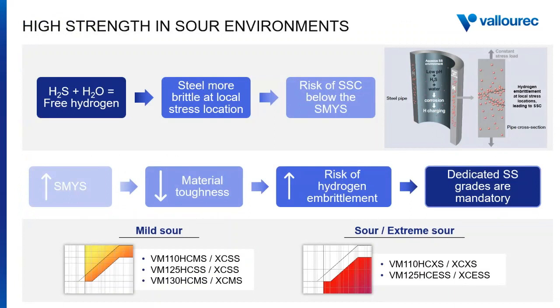This is related to the discussion we had on this slide, because we said that when the material becomes more brittle, then the risk of cracking due to the presence of H2S becomes greater. Another thing we need to consider is that the material also becomes more brittle at low temperature. Normally when we talk about the sour service resistance of a material, it is because we perform the NACE test at the lowest temperature the material is expected to see, either room temperature or seabed temperature.